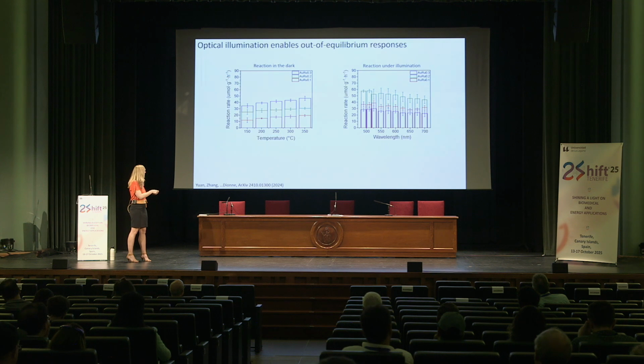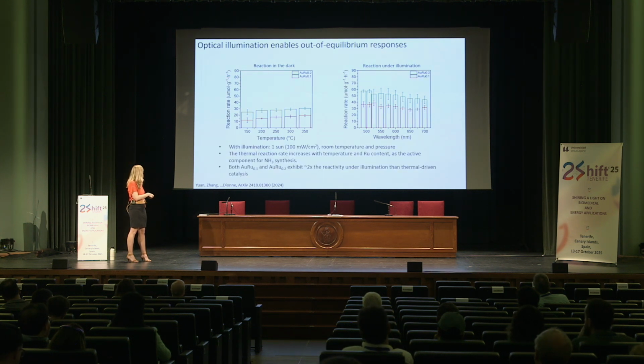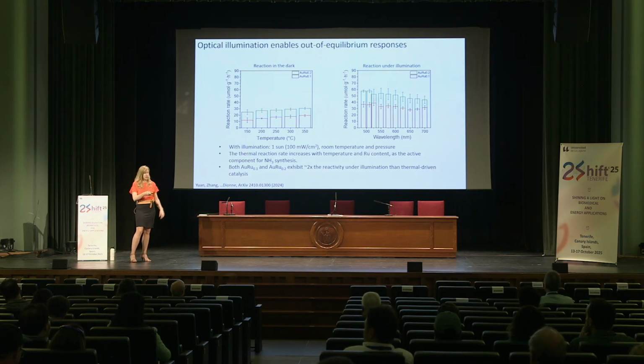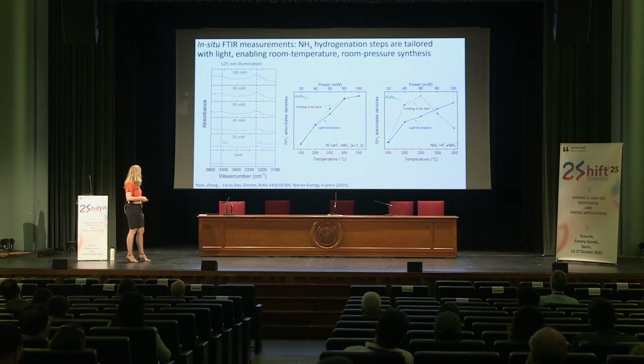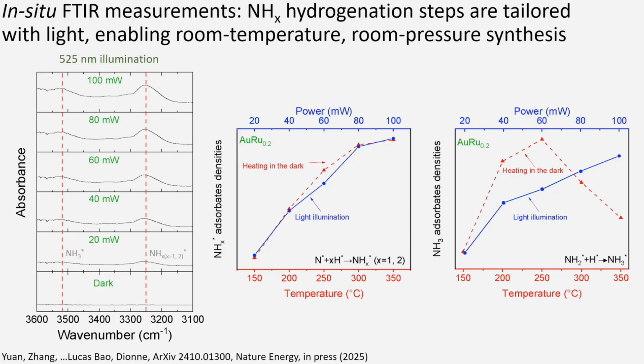But either way, when we have this optimized system, where we have 20% ruthenium, even just with one sun illumination, room temperature, and room pressure, we have almost twice the reaction rate as you can get with higher temperatures and higher pressures. And what we've done is also combine these reactor scale experiments with in situ FTIR spectroscopy to look at the intermediates.